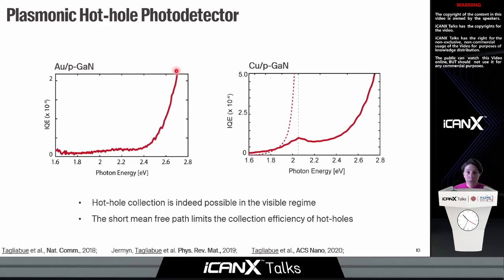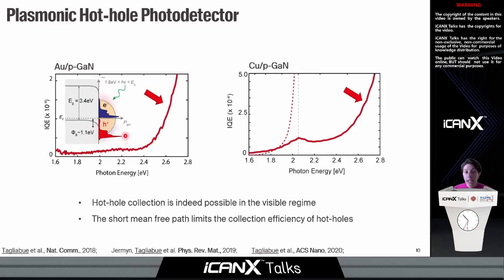So the first feature that we observe is that indeed, for very high photon energies, we have a steep rise in the photocurrent. This is telling us that for very high photon energies, we have a very large probability of generating high energy hot holes, and that these hot holes then are transferred into the semiconductor, resulting in this very high photocurrent response. So this is indeed telling us that despite the fact that they have very short mean-free path, we are able to collect them when the photon energy is sufficiently high. At the same time, this dashed line shows what we would have expected for a Fowler injection model for holes with increasing energy. And so the fact that we observed this steep rise at a higher photon energy than initially expected is telling us that indeed there is an intermediate regime where the mean-free path is a limiting factor for the collection of the holes.